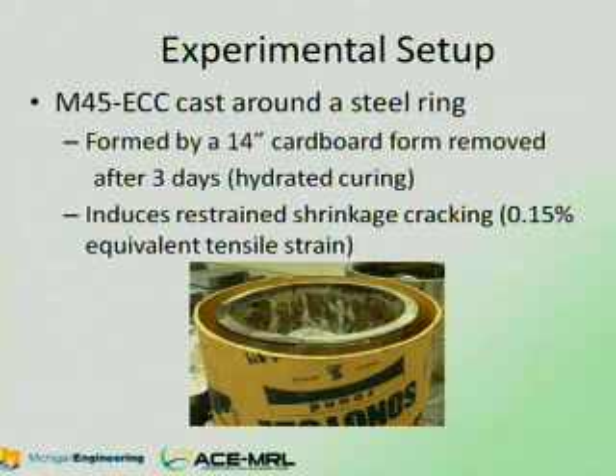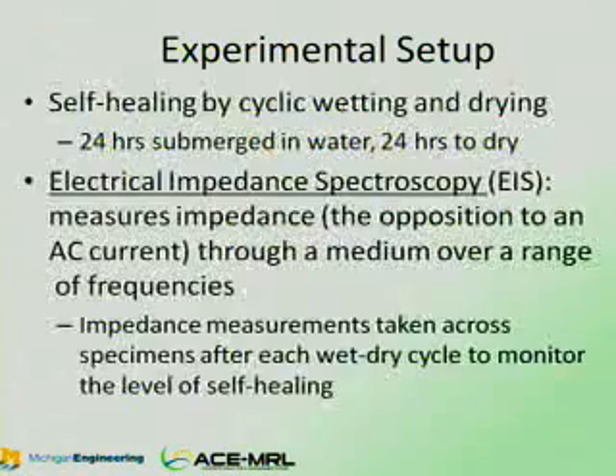The first thing I did in my experiment was mix and cast ECC specimens around a steel ring, formed by a 14-inch cardboard tube form, removed after 3 days. This is where I am right now in my experiment, waiting for the shrinkage cracks to form before I take them off the steel ring. This induces restrained shrinkage cracking, about 0.15% equivalent tensile strain.